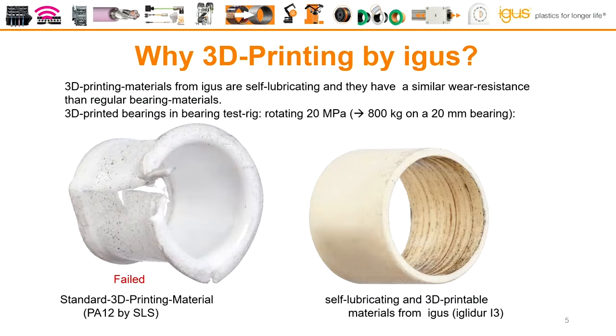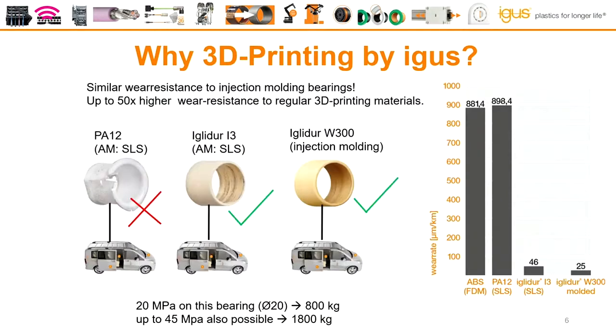The left one is a regular printing material. It is PA12 by laser sintering. And the right one is our iglidur i3 with the solid lubricants. It was about 20 millimeters in diameter and length, and there was 800 kilograms of load on it. And you see the regular printing material fails very quickly. It failed totally. And with the iglidur i3 material, we have only very little wear here. And that is the big difference we have with our 3D printing materials from igus.